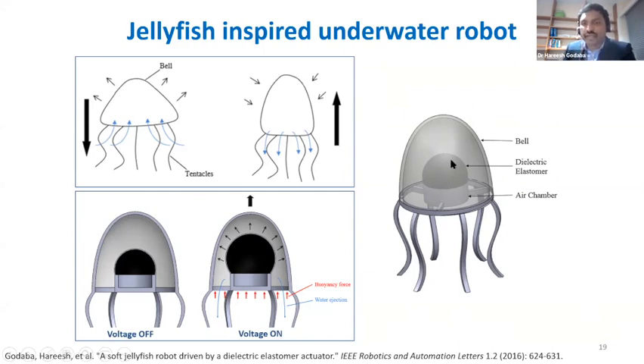Now, when we apply voltage to this elastomer membrane, the membrane increases in volume. And when this increases in volume, there are two forces that are generated. First, the fluid is pumped out from the bottom through the apertures here. This creates thrust force. And then because the volume of this membrane has increased, it also creates some additional buoyant force that can make this robot move up, right? So we basically looked at these two types of forces.